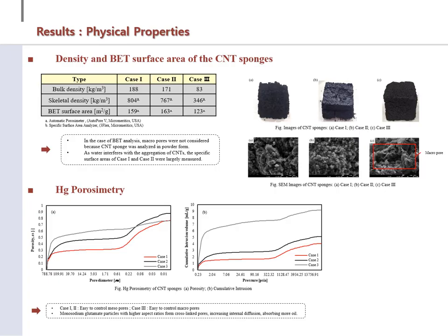I will show you the results for the prepared absorbents. Bulk density of the prepared absorbent ranged from 188 to 83 kg per cubic meter depending on salt content per CNT. As the mass ratio of salt per CNT increased, the skeletal density decreased, indicating an increase of the internal pore volume of the absorbent as shown in the mercury porosimetry result. Case 3 showed the highest pore volume in this study because needle-like glutamate makes large and long pores inside the absorbent.